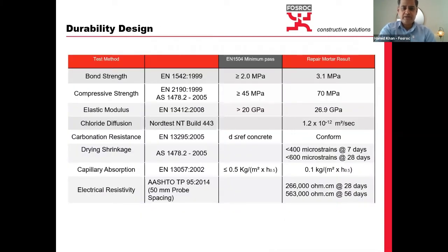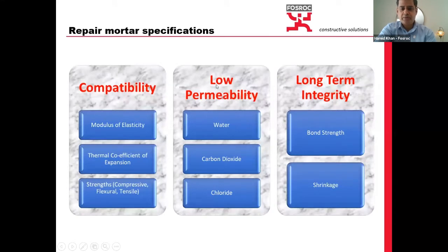This is a typical repair mortar specification. This is one of many others as well. So as I said, the carbonation resistance should qualify EN 13295 standard. The chloride diffusion test is very important. So these two testing parameters come, if I go back, under low permeability. So it's very important to understand that when we say low permeability of repair mortars, that means they should be low in permeability against these corrosive agents.